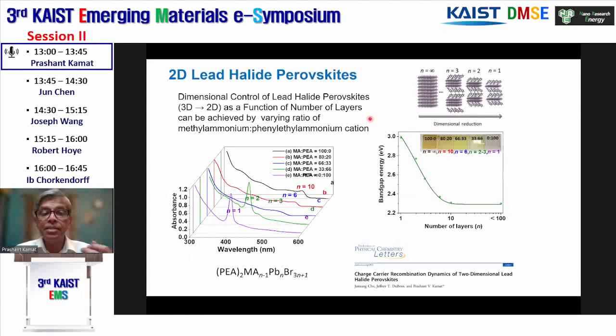So how you make it is you just change the ratio of your spacer cation and your methyl ammonium cation, and that gives you different layers. For example, if you're 3D and you add a little bit, in a controlled fashion, change the ratio between methyl ammonium and phenylethyl ammonium cation, and you start separating out these layers. When you have 100% PEA, then you get n equal to 1. And when you have 33 to 66, you get n equal to 2, etc.